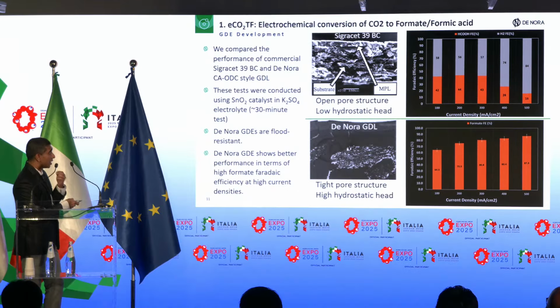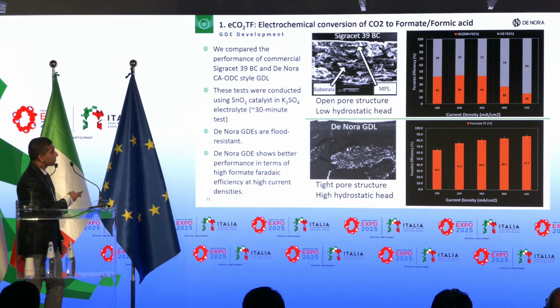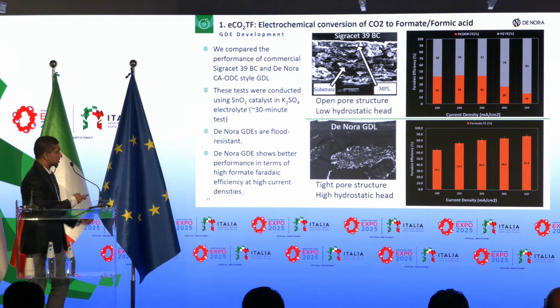There are two sets of gas diffusion layers I'm comparing here. What you see on the top, maybe familiar to some of you, is called the Sigracet 39BC. This is a commercial fuel cell type gas diffusion layer. When you look at the cross-section of this gas diffusion layer, you see a very open pore structure, which can result in low hydrostatic head. That means if you have a water column next to the MPL side of the gas diffusion layer, the water can slowly penetrate into the gas channel.